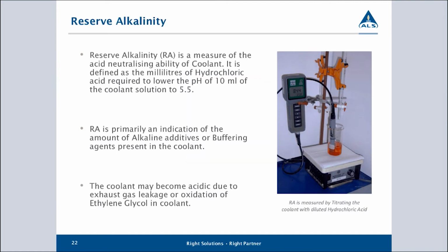Reserve alkalinity is a measure of the coolant's ability to absorb acid. Coolants don't normally get exposed to much acid from the environment, that type of thing. But there is one potential problem with the coolant, and that is that your glycol, when it degrades, can thermally decompose, and it will start doing this at as low as 80 degrees Celsius. When this thermal degradation occurs with glycol, it does tend to produce acid components.